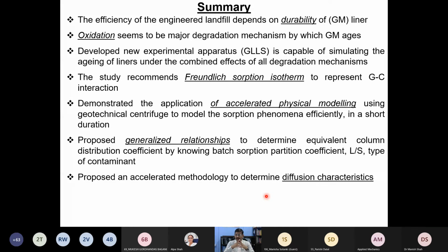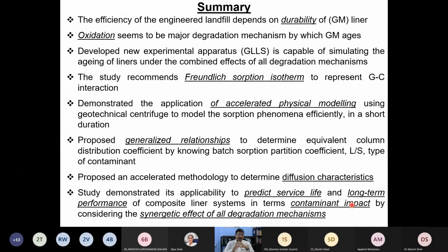We also propose the accelerated diffusion methodology to get the diffusion coefficient, and then finally we demonstrated very nicely how to predict the service life, and how the service life prediction is impacting the long-term performance, and from the contaminant impact point of view, by considering all synergistic, not only the environmental conditions, all degradation mechanisms also we have considered.